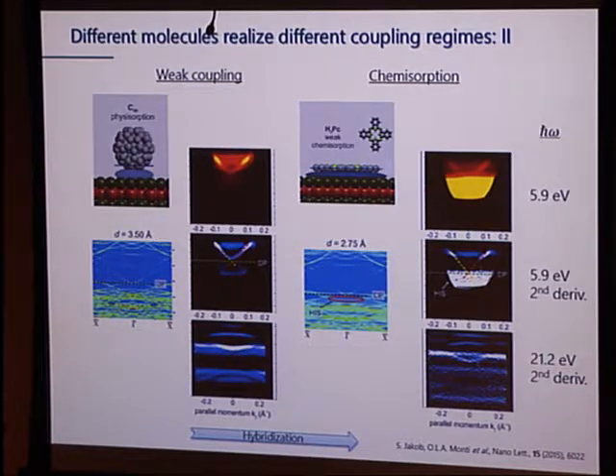Compare and contrast. Right? So here we have basically the Dirac cone structure and not much else. You still see now there is a presence of the Dirac cone, but there's also this very strong new band here, and that's exactly this hybrid interface state. It is not dispersive. It is really quite flat, that's the hallmark of this hybrid interface state, and also the Dirac point shifts around. So that would be chemisorption.